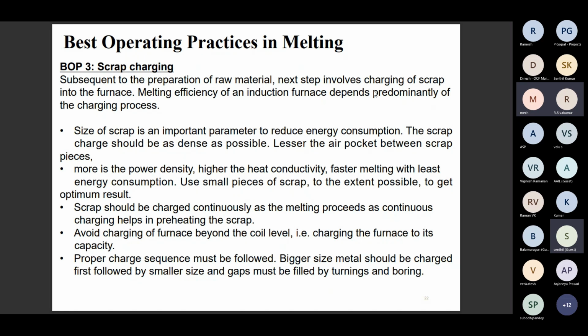Use small pieces of scrap to get the optimum result. Scrap should be charged continuously as the melting proceeds, as continuous charging helps in preheating the scrap. Sometimes, if it is possible, preheat the scrap up to 60 or 70 degrees, so that the furnace energy